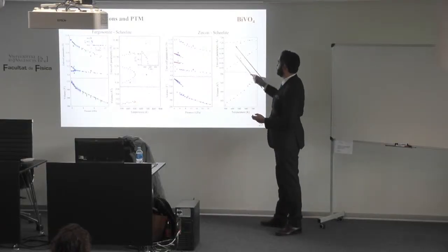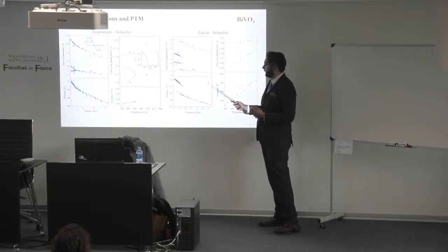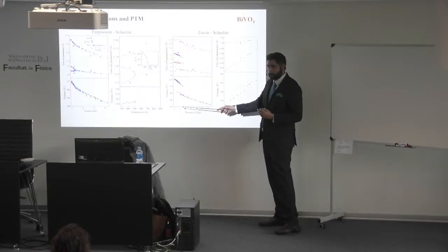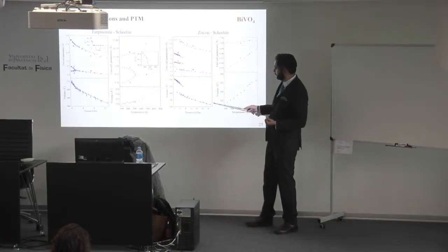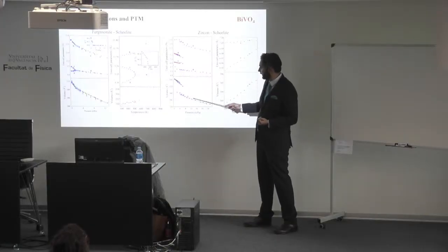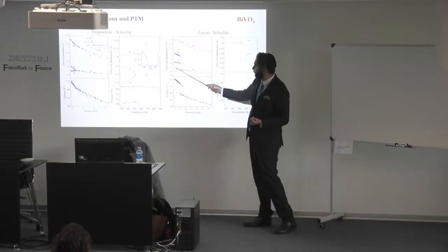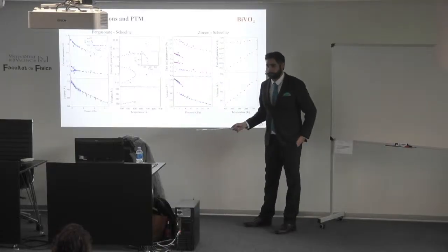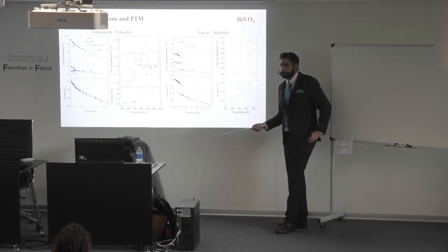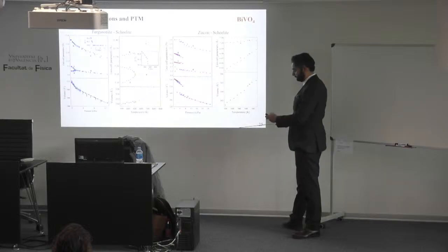In the case of the zircon-scheelite phase transition, it happens at around 6 GPa. It's non-reversible, so if we go back, we still have scheelite, and at the end, we saw Fergusonite. So the natural one indeed is the Fergusonite structure.